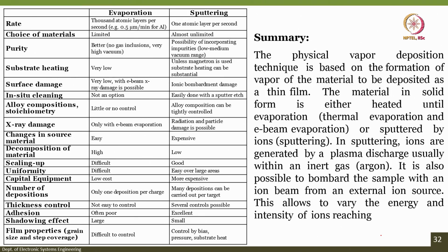Third one is purity, right, evaporation is better because no gas inclusions, very high vacuum. But in the case of sputtering, the vacuum is low or medium range, and that is why the purity may not be as good as the evaporation. Substrate heating is very low, unless magnetron is used, substrate heating can be substantial. If magnetron is used, substrate heating will be comparatively lower. Surface damage, there is a surface damage in the case of e-beam because of the generation of X-ray. Here the ion bombardment may damage the surface, otherwise there is no generation of X-ray. In situ cleaning, it is not possible in case of evaporation, but in case of sputtering, you can clean the chamber by sputtering, with the sputtering itself.